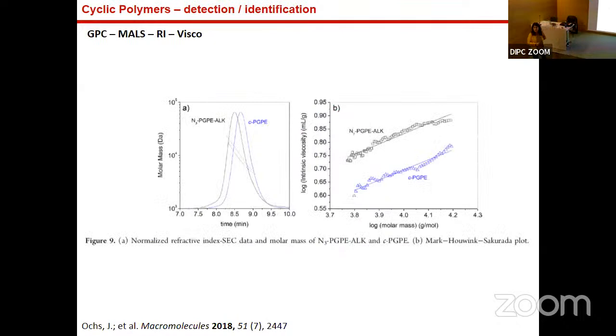GPC also, but with a triple detection. This is multi-angle light scattering, refractive index, and viscosity. Here is the typical shift in the GPC data after the formation of the cyclic polymer. And these are the viscosity data in solution, for the precursor and the cyclic polymer. They show reduced intrinsic viscosity, with a ratio which is in agreement with the literature, about 0.8 or 0.7, I think, in this case. So this is a demonstration of also having obtained the cyclic polymer.